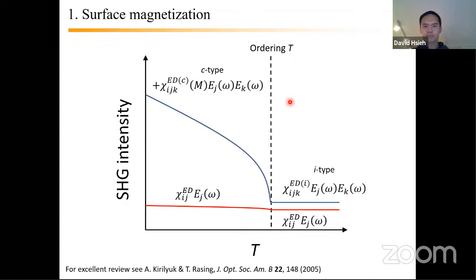So if you have a material, for example, that preserves inversion symmetry crystallographically and acquires a surface magnetization below some critical temperature given by this dashed line, then generically what you might see is that above TC, with TC being, let's say, the Curie temperature, there's some higher order response, maybe an electric dipole surface response, that comes from the crystallographic structure. And that response is I-type. I-type just means that this tensor chi-ED is invariant under time reversal operation.